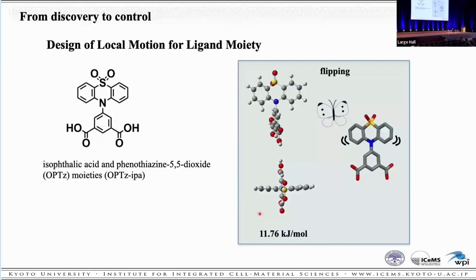We also calculated the flipping energy of the OPTz ring. The results show that the ligand has extremely low flipping energy. As a control, the vibration energy for cyclohexane is 46 kilojoules per mole, indicating that the ligand is somewhat flexible and quickly changes its configuration.